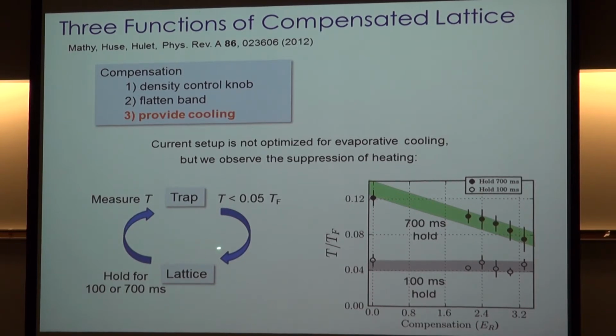But a priori, the way we measure the temperatures is to do it in the trap. Then we adiabatically turn on the lattice. We hold for some amount of time. Then we adiabatically turn off the lattice and remeasure the temperature. And all of this is because there's no good thermometer in the lattice. So we measure temperatures to start with that are around 0.05. And as long as we don't hold for too long, the temperature remains pretty low.